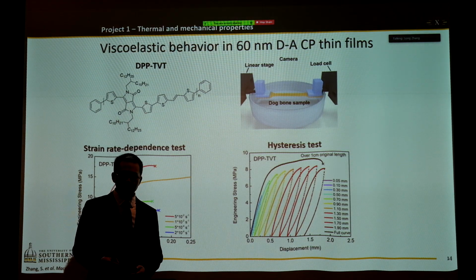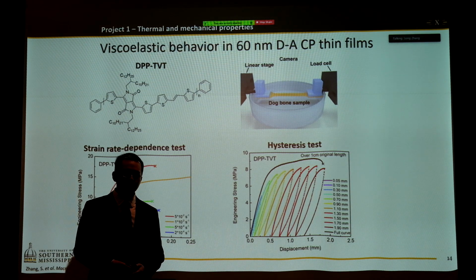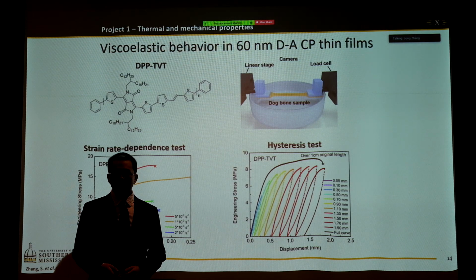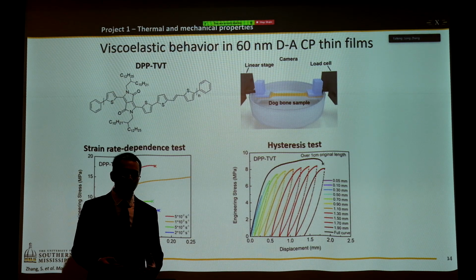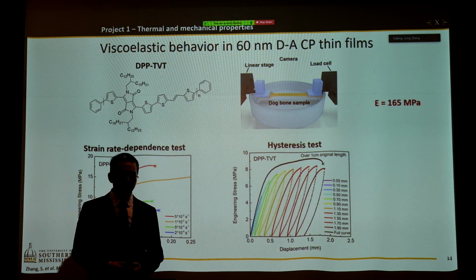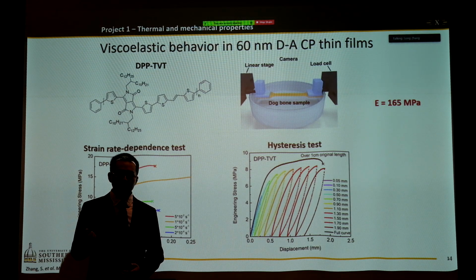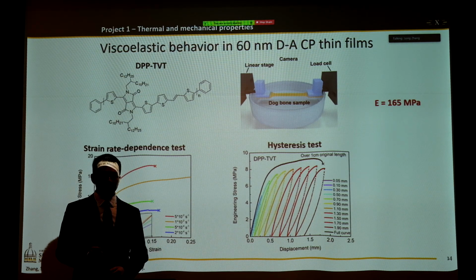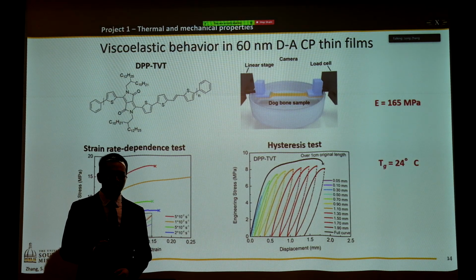However, when we start to measure these polymer thin films on top of water, we find out it's very viscoelastic. As you can see, the strain rate dependent elastic modulus, the hysteresis, and the plastic strain. Well, the modulus is actually super low. It's around 165 megapascal, and when compared with traditional polystyrene, with only one six-ring structure in polystyrene, the modulus is 20 times higher. So why is that? Later, we attributed the low modulus to the low glass transition temperature around room temperature.